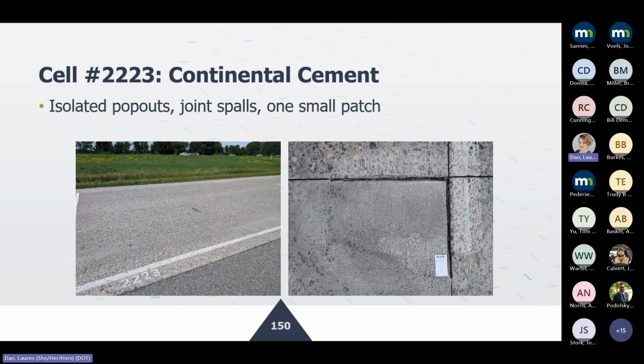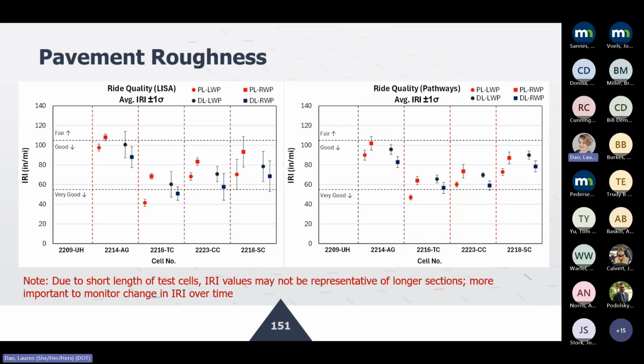And then continental cement, again, we did see some isolated pop-outs and one small patch, I think this was to repair a misaligned tie bar. Yeah, there was a misaligned tie bar at this particular location, and we did see one small patch there. But other than that, no cracking, isolated pop-out areas, and seems to be doing pretty well after year 1.